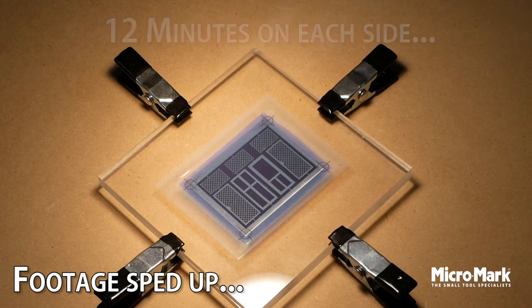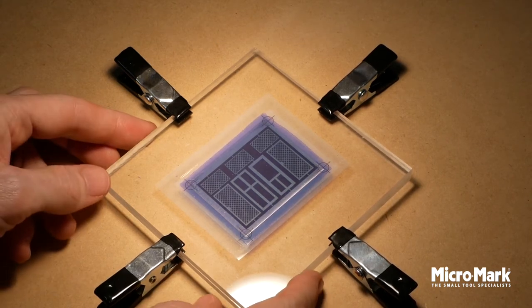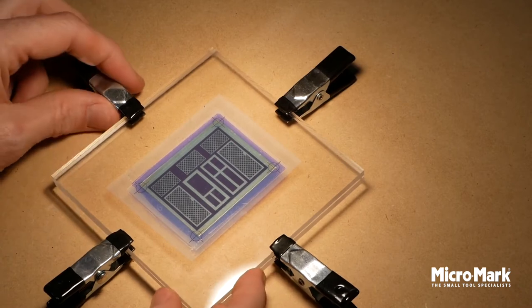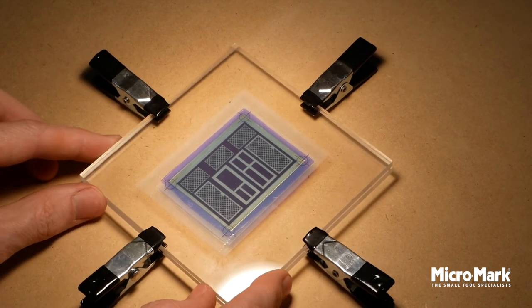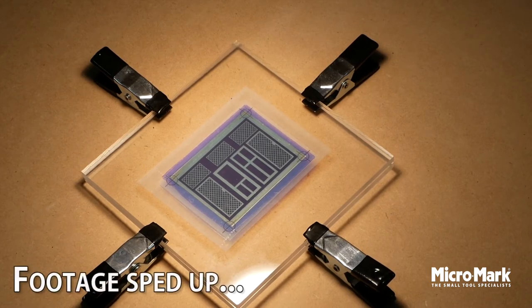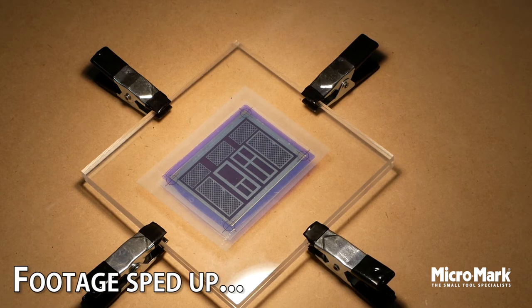It will gradually turn a medium purple color and once the timer goes off I flip the plate over and cook on side two for another 12 minutes. If you're wondering how I got 12 minutes it's from doing a few test pieces. I did one at 10 minutes and it wasn't quite enough and another I did for 15 minutes and some of the black area started to become exposed so 12 minutes it was.